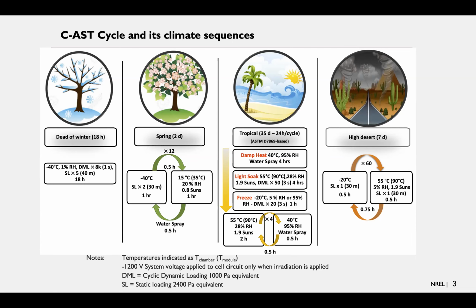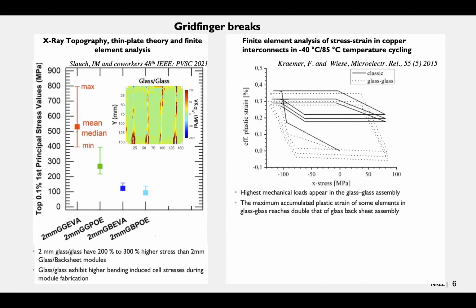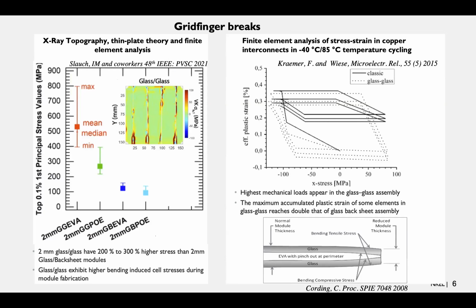I'd also like to point out that I don't think what we found was out of the ordinary or totally unexpected, because prior results in the literature, including those out of DuraMAT, show some consistencies where glass modules have higher principal stresses, especially around the metallization, where there'd be grid finger breaks. So I don't think what we saw was, I would say, out of common sense.